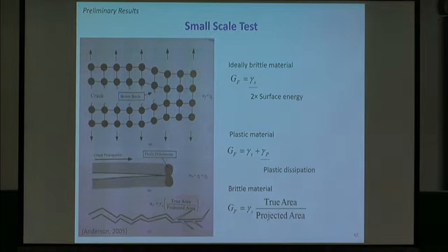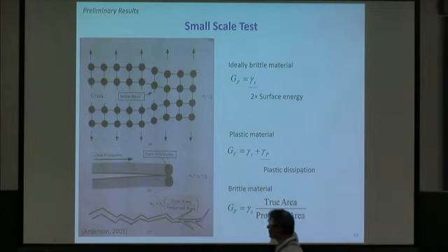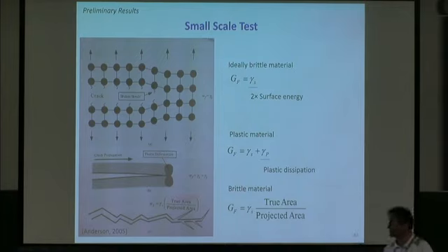We know, of course, if you start going back to theory here, if you go to microscale all the way down, you can consider the fracturing as breaking of bonds, either covalent bonds or hydrogen bonding and so on. And typically, if this was an ideally brittle material, you could have the fracture energy related to the surface energy multiplied by 2. But when we talk about a more plastic material, and we can't expect that sea ice is ideally brittle, you more have to consider that there are things happening in this area, which is not just related to breaking up the ice you have. You have pore water in there. You have a porosity, which can be also relatively high in sea ice. So it's quite complicated.